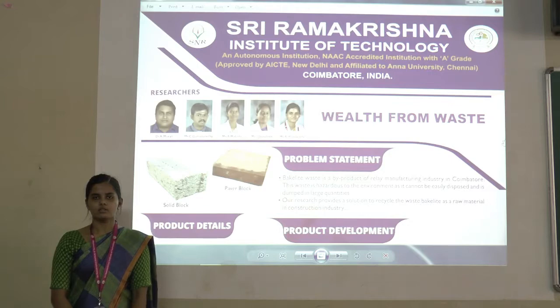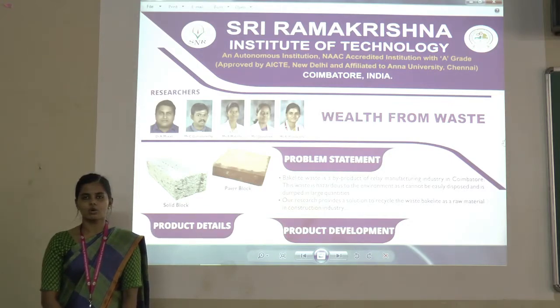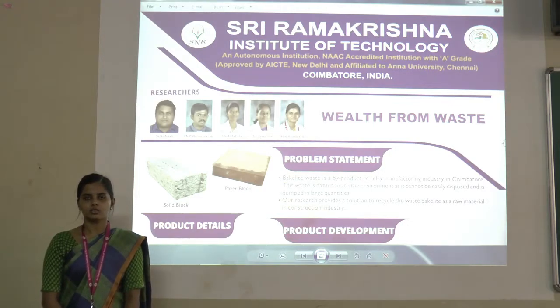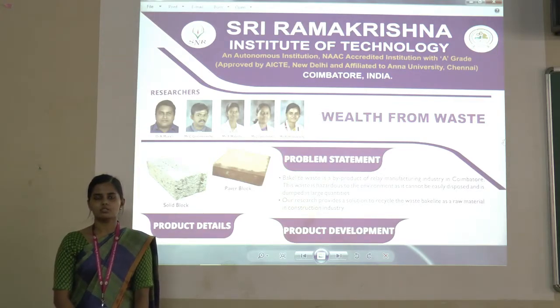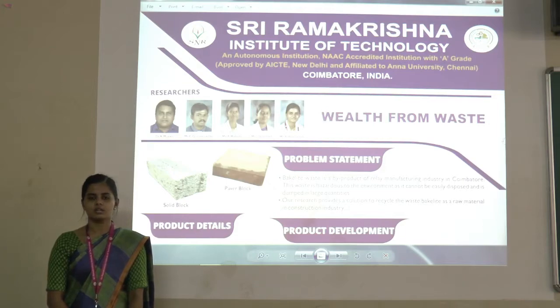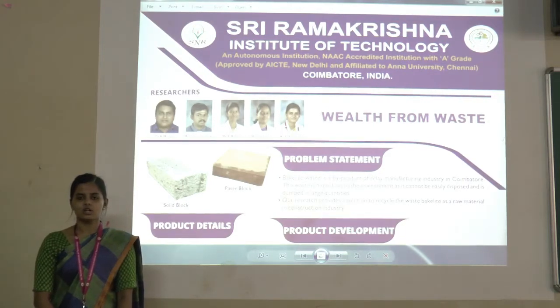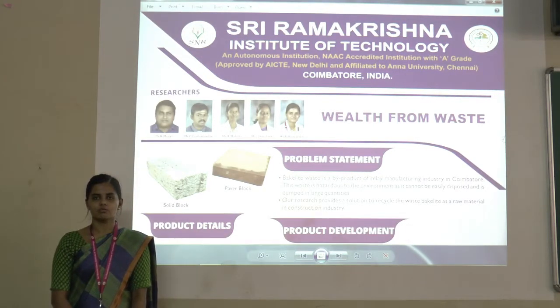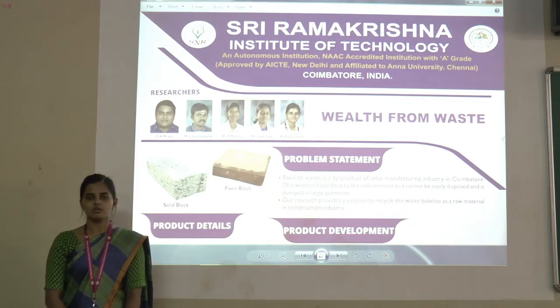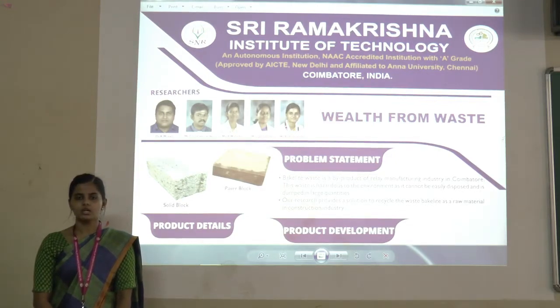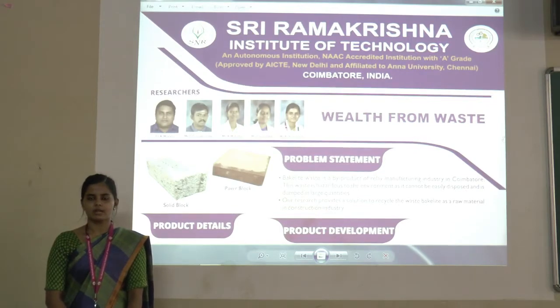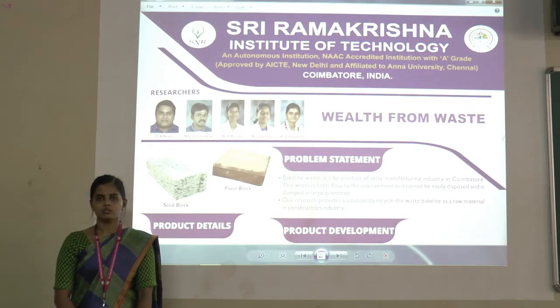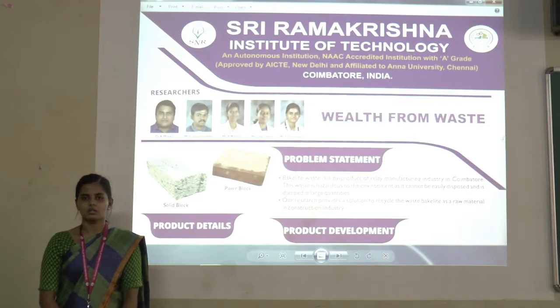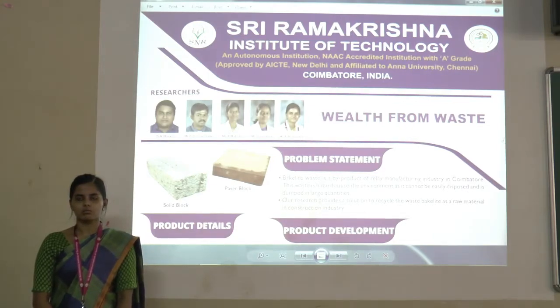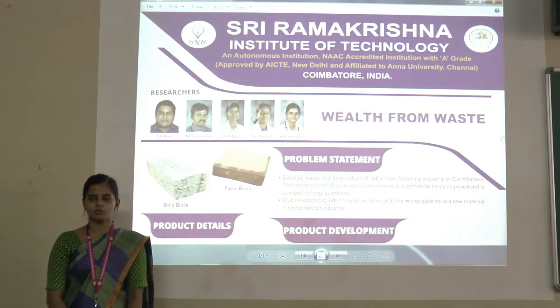After casting this solid block, we are going to test it in three tests, that is bulk density, compressive strength and water absorption test. From these results, we have observed that a compressive strength of 4.71 Newton per mm square has been achieved with the partial replacement of Bakelite, and the conventional compressive strength for solid block is 4.5 Newton per mm square.